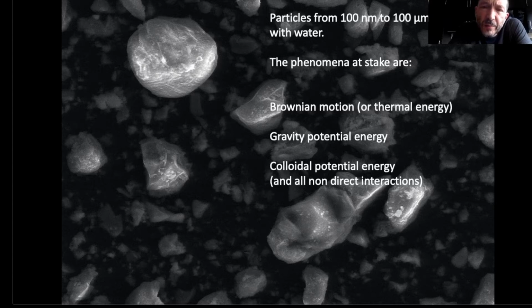The phenomena at stake that have been identified are Brownian motion or thermal agitation, gravity potential energy due to the difference in density between the cement grains and the liquid, and colloidal potential energy for this type of size. 100 micrometers is quite big for colloidal particles, while 100 nanometers is really a good range. These create some non-direct interactions, repulsive or attractive.